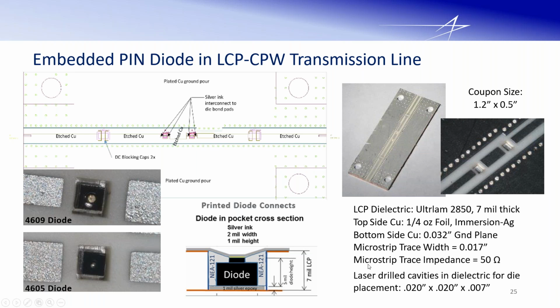And what we're doing, we use that same NEA 121 dielectric, the printed dielectric, and we encapsulate the die, just leaving the bond pad exposed. So this is something that you kind of need a UV curable adhesive. If it wasn't UV curable, where it can kind of be cured out of the nozzle, you'd end up covering this bond pad. So in this case, we could dispense it, fill in around the diodes, but leave the bond pad clear. And then we would print a trace that kind of goes right across the transmission line to the bond pad to the other transmission line.